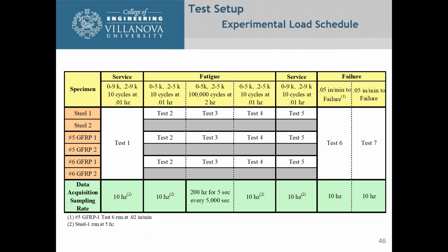Here's all the different testing that we did. Remember, we said we had 2 steel, 2 GFRPs, and 2 number 5 bars and 2 number 6 bars. And the way we tested every one of these was, first test was under service load, 10 cycles, very slowly. And what this was to do was to say, okay, we're going to put it under service load and essentially break the beam in and let it do whatever cracking it's going to do under a service load condition. Very slowly, just kind of put some load on the beam.